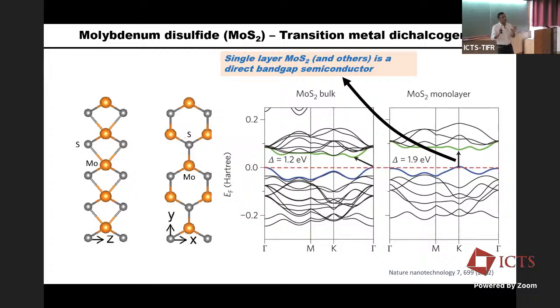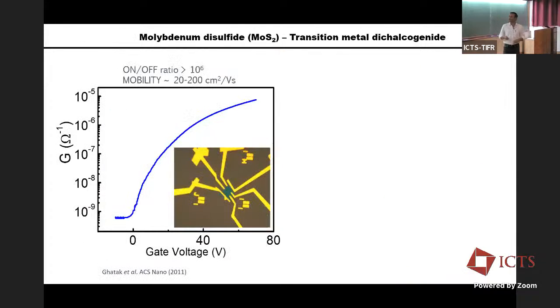For the first time now, we have a beautiful semiconductor with which we can make devices and overcome certain difficulties that we had in the case of graphene. So this is our work long time back, about a few months after the original paper on molybdenum disulfide came out. You can see that as you change now the gate voltage, the electrical conductance changes by orders of magnitude.